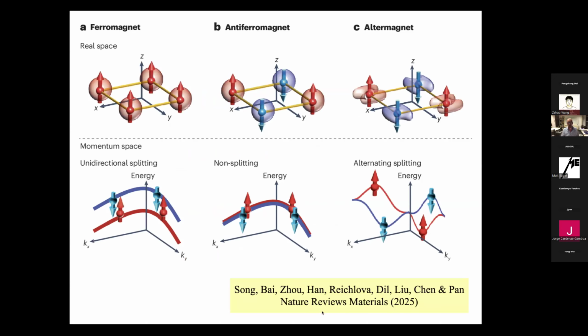And recently, the answer was yes, at least by part of the magnetic community. It's argued to be yes, because there's the altermagnet. I'll explain in the rest of the talk what an altermagnet is, but I'll give you a first impression here. In a ferromagnet, we have all spins aligned in a particular direction, which means that in momentum space, in the band structure, in k space, the energy bands are split. If there is no spin-orbit coupling, one can assign a spin to each band. So this red band has spin up, and this blue band at a different energy has spin down. In an antiferromagnet, there is no net magnetization, and in general also no spin splitting of the bands. The bands are degenerate everywhere in momentum space, at least if there's no spin-orbit coupling.